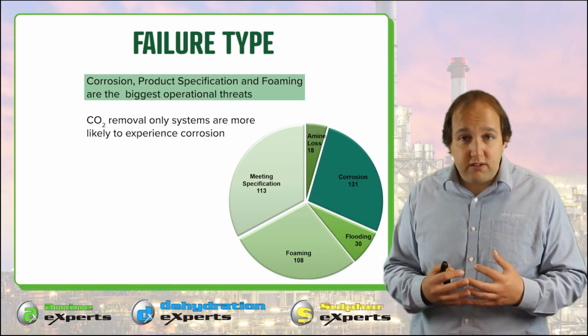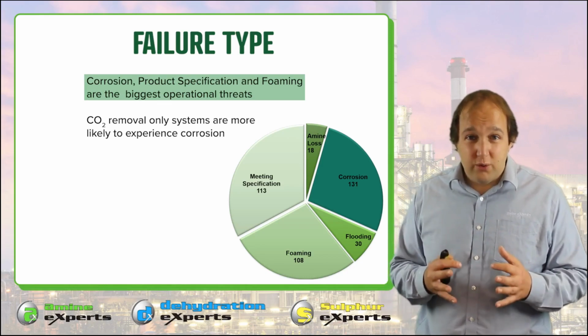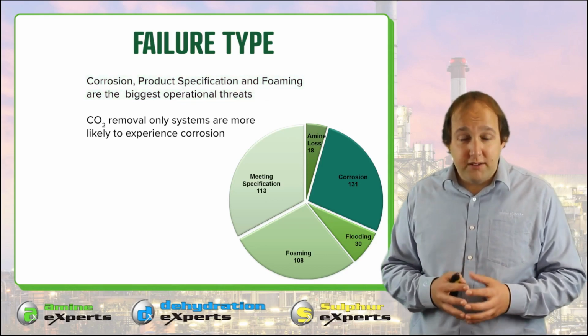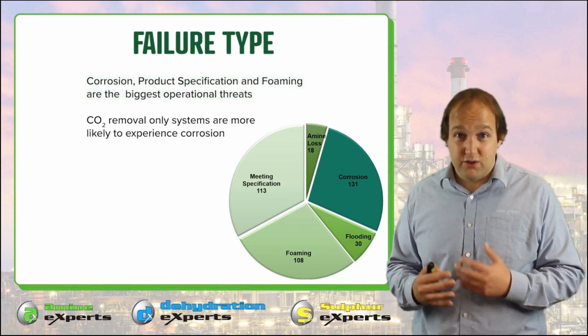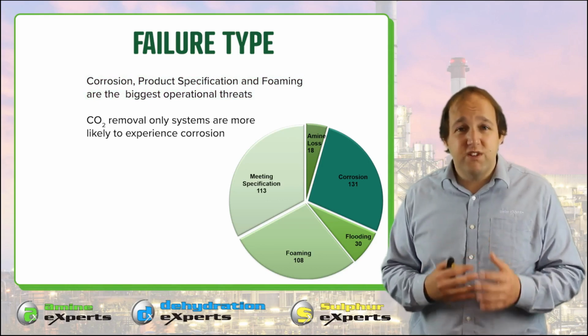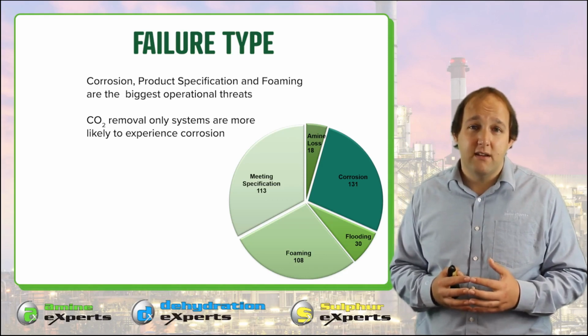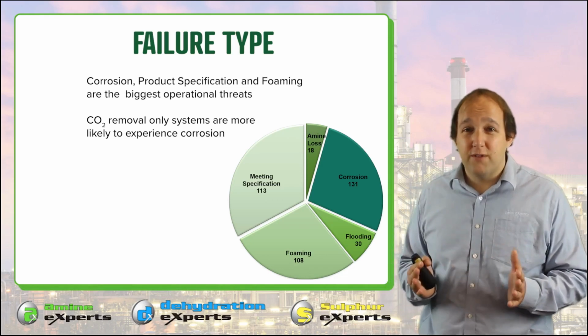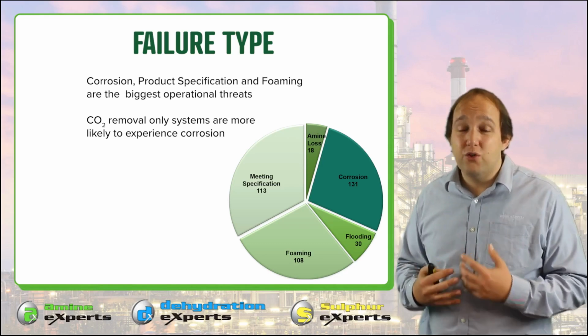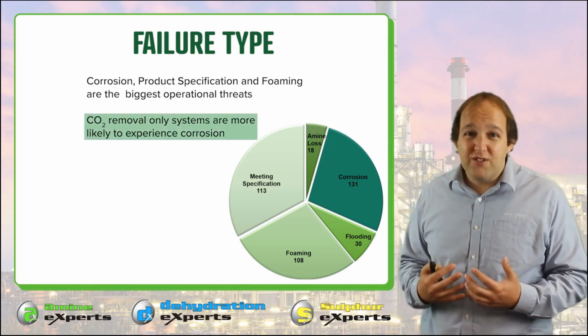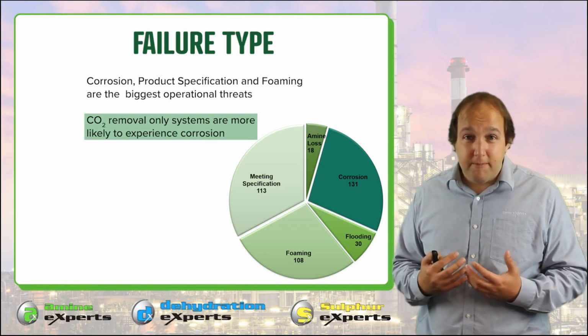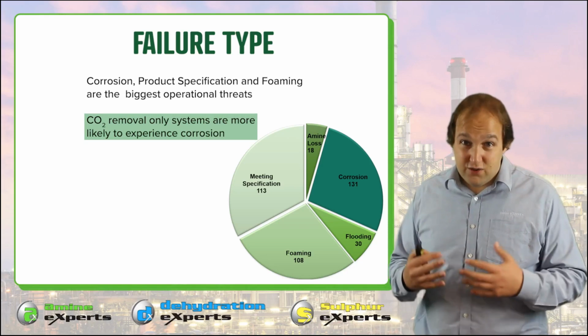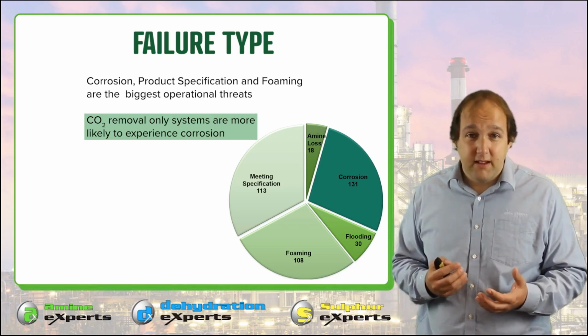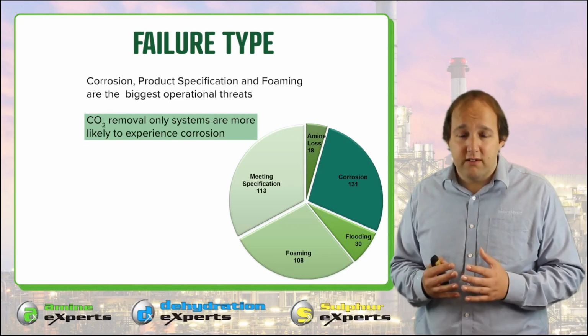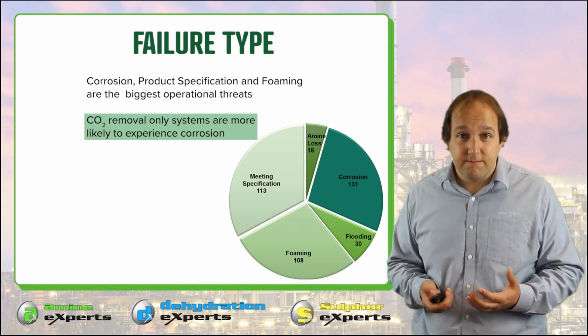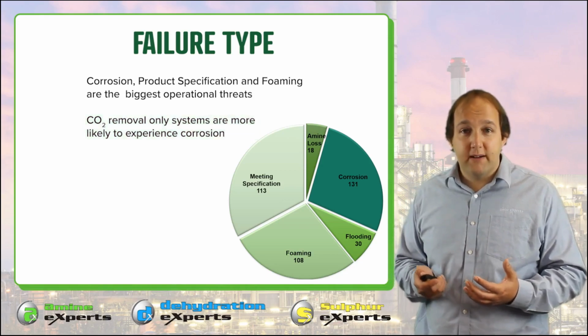Now, the first trend that we actually saw was that there was a difference between plants that were predominantly processing CO2 and those where there was significant H2S present in the feed gas. And that difference really was the proportion of failures that was caused by corrosion. So in CO2 service, more production failures were observed as a result of corrosion than in service where H2S was in the feed. And this difference is quite important when you're looking at these different systems. So the first thing we're going to talk about is corrosion.